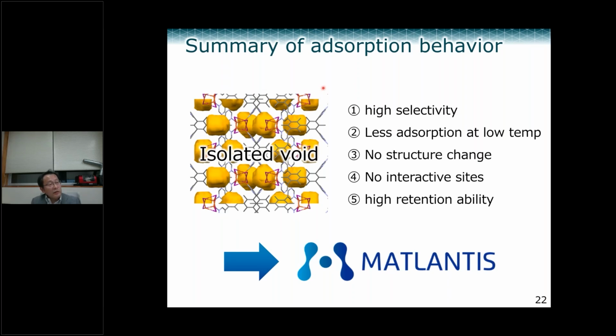Let me summarize the nature of this material for CO₂ sorption. This material has a high selectivity for CO₂ over dinitrogen. At low temperature, this material cannot absorb gas molecules. Surprisingly, there is no structural change. And even though there is no interactive site in the void, this material has a high retention ability. Then we decided to investigate the sorption mechanism using Matlantis.